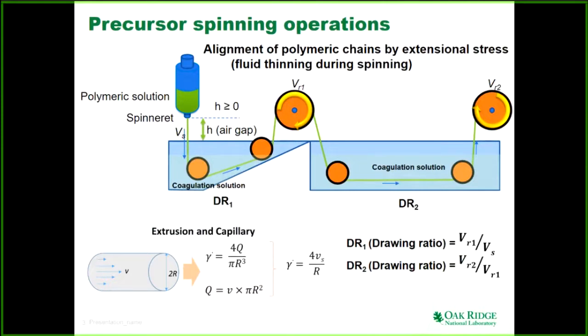Now, we are trying to understand how we can pull it better, how we can increase its elongational viscosity. That is, again, the entire theme of this particular research. And if we can increase the elongational viscosity, that means tolerance to stretch or extensibility, then we can increase the VR, rotation speed. So if we can increase the rotation speed, using existing equipment, you can increase the production throughput. Not only that, when you are increasing production throughput, your fiber is also getting more aligned along the fiber axis direction. And if you have higher V1, then you can gradually increase the speed of production in every stage.